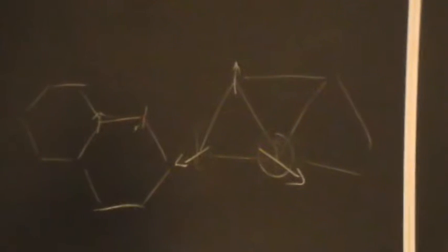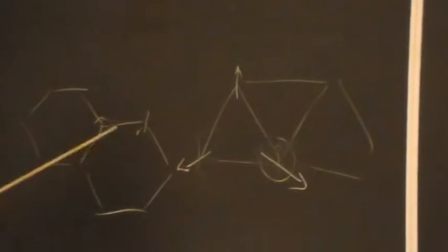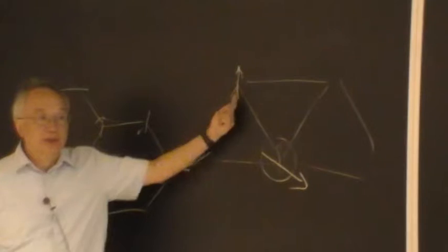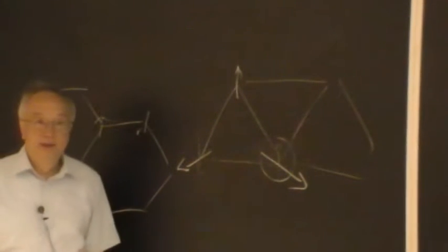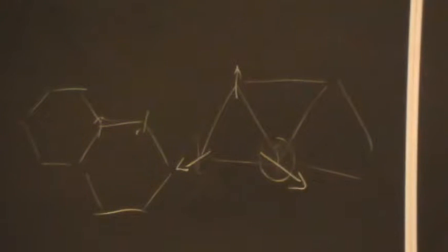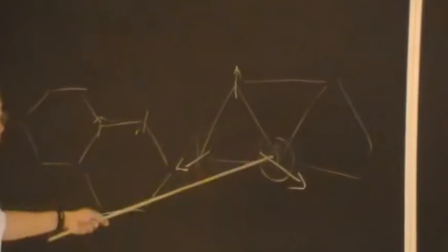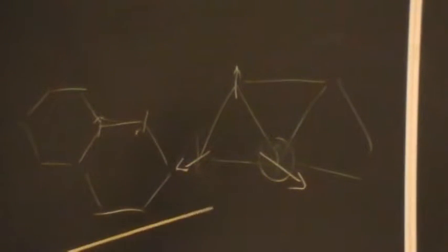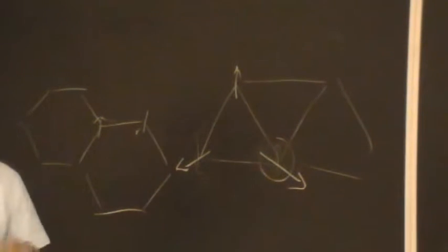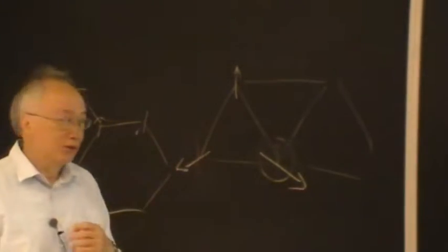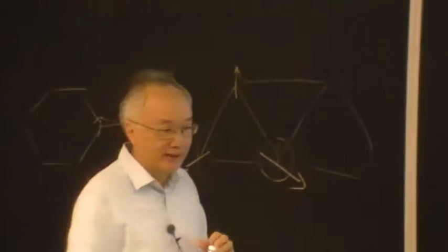And it turns out that for the Heisenberg model, there is a way of relieving this frustration, because the picture was actually for Ising spins, just like that. But this is a Heisenberg spin, so they could compromise by pointing 120 degrees to each other. So each one would enjoy some of the antiferromagnetic energy, even classically. So it is not truly frustrated in that sense. You can have a compromise. And so I think now it's established pretty much this is the true ground state, with a very much reduced moment. The ordered moment is much smaller than the classical one, in Bohr magnetons. I forgot what the number is. So it barely made it. So once again, triumph for the ordered state.